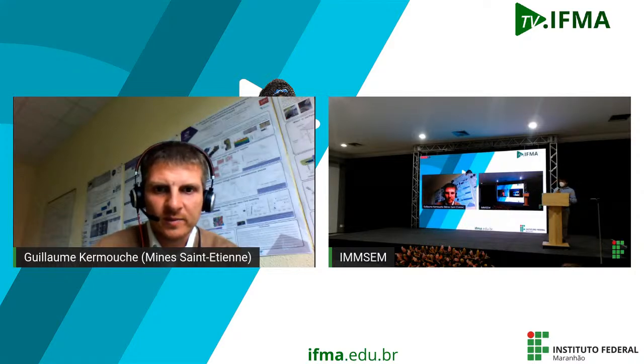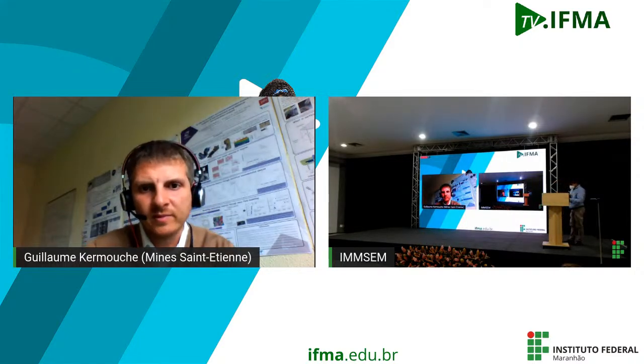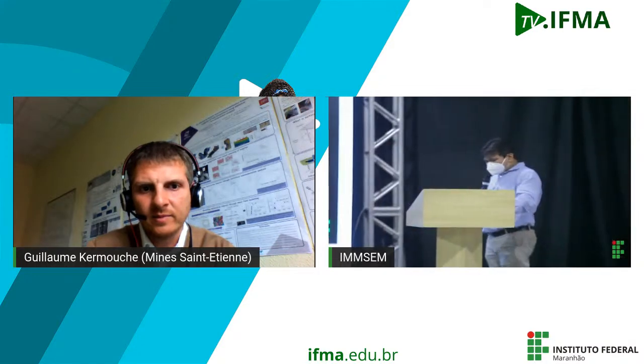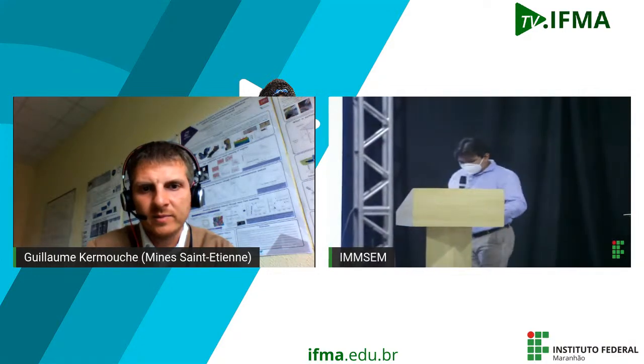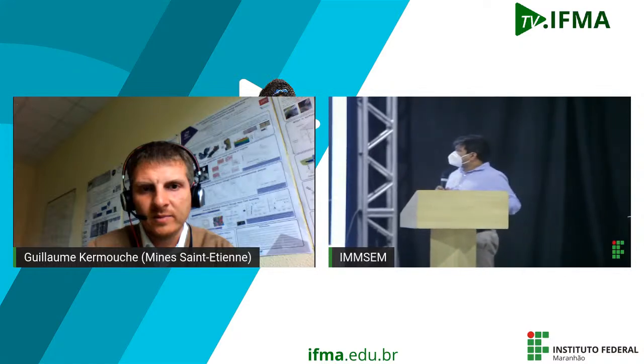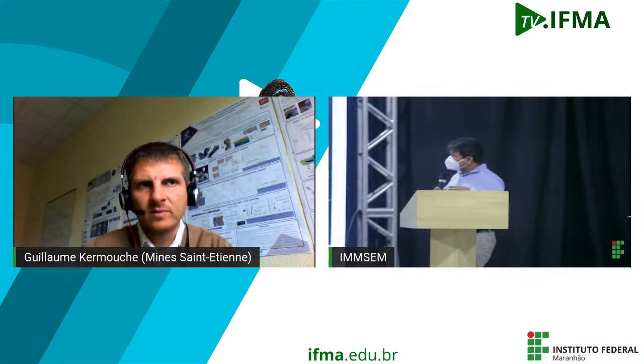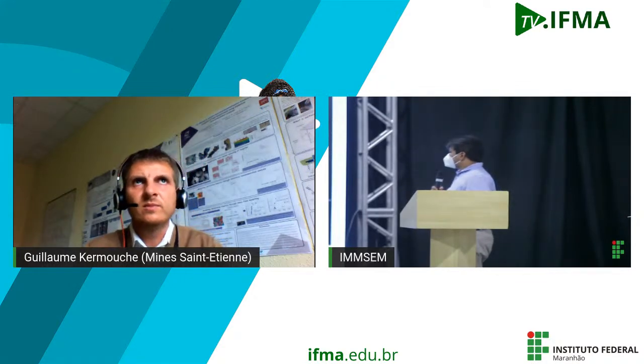No question? I have a question, Professor. During your presentation, an amazing result that surprised me a lot was the softening that happened in the material. We see that the density of dislocation decreased, but this normally leads to a higher hardness. And in the tungsten, we saw that the recrystallized grain led to higher hardness. How could you explain this? Like that's the opposite of what normally happens to metal alloys.